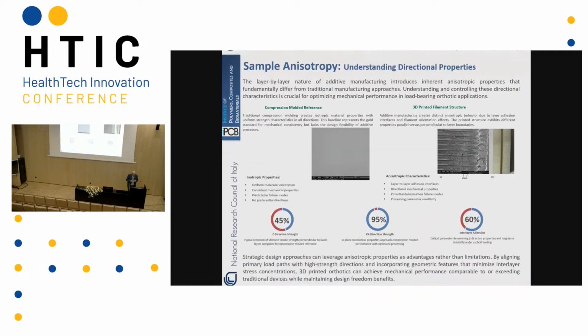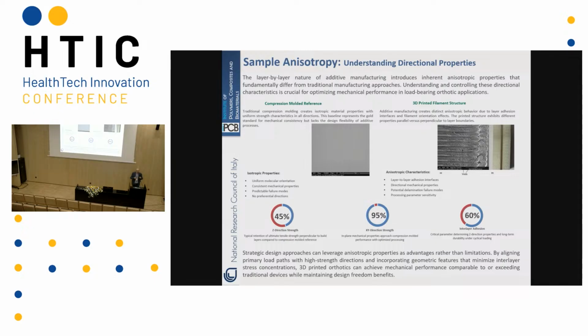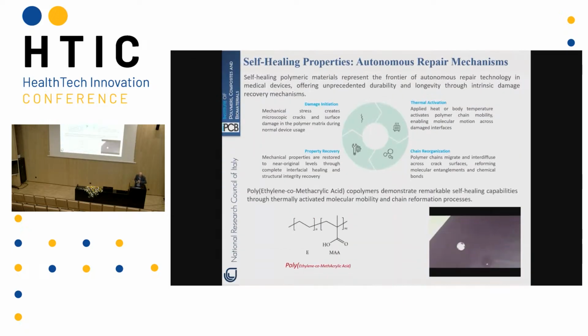It can be improved, of course, by increasing temperature or changing some parameters, but generally the difference is not so high. If we compare results obtained with classical compression molding and 3D printing, you find that the differences in the mechanical properties are very important, especially in the Z direction, the direction of growth of this part. Of course, you can change the position of your part in the printer. You can be so lucky as to align the load direction of your object perpendicularly to the growth direction. But also in this case, it's very difficult to obtain results comparable to those we find with other technology.